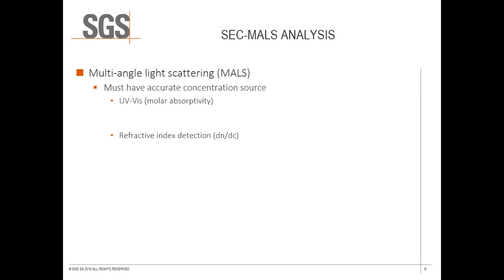The characteristics of each sample must be considered before beginning experimentation. If the sample is UV active, then the molar absorptivity must be known or measured in order to use UV-Vis as the concentration source. And a mobile phase must be chosen that will not contribute to light absorption at the chosen wavelength. For the use of refractive index detection as the concentration source, the differential refractive index increment of the sample must be known or measured.